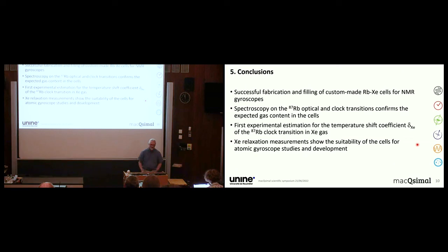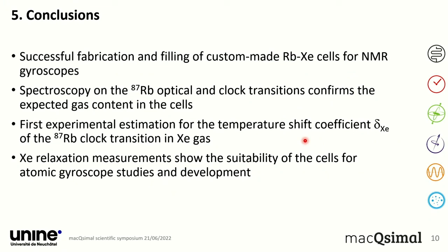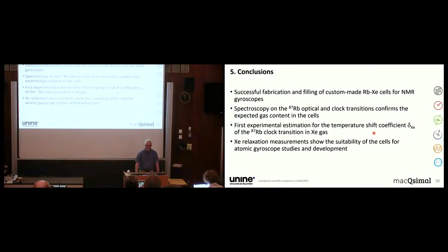So in conclusion, we had successful fabrication and filling of our custom-made rubidium Xenon cells for the NMR gyroscope studies. And we could do the spectroscopy on the rubidium-87 optical and clock transitions to confirm the expected gas content in the cells. The first experimental estimation for the temperature shift coefficient that we could extract from these cells, the delta coefficient for the rubidium clock transition in xenon gas, is quite interesting, and it coincides with the expectations and predictions from other publications. And with this, we could hand the cells over to Bosch for the gyroscope studies and developments.